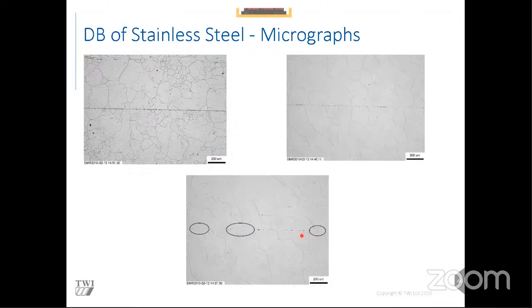You can only see a few voids, but more importantly, you're seeing grain growth across the boundary - very clear signs of grain growth. So that's a good example of a diffusion bonded joint. The size of the pores isn't too dissimilar from the size of the intermetallics or pores in the parent material anyway, so it's very difficult to see.